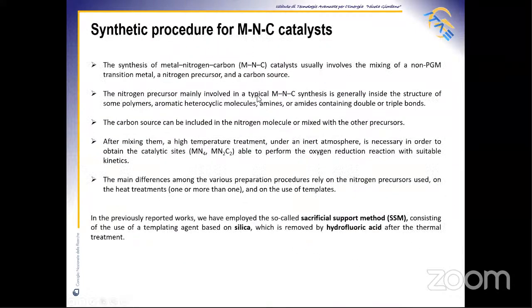A synthetic procedure for metal nitrogen carbon catalyst generally involves the mixing of metal, nitrogen precursor, and carbon sources. The nitrogen precursor is generally inside the structure of some polymers, like aromatic heterocycle molecules, amines or amides, containing double or triple bonds. The carbon source can be included in the nitrogen molecule or not.